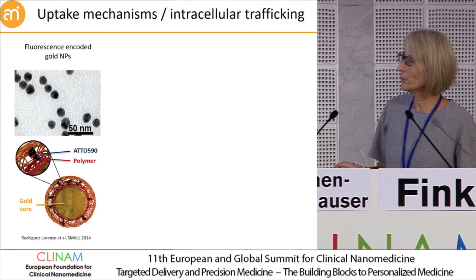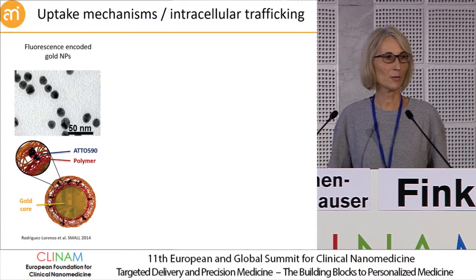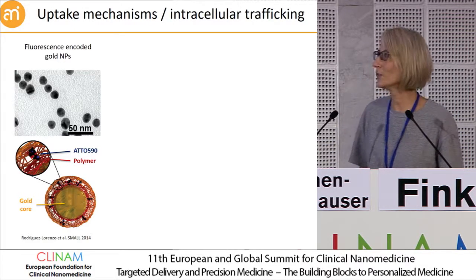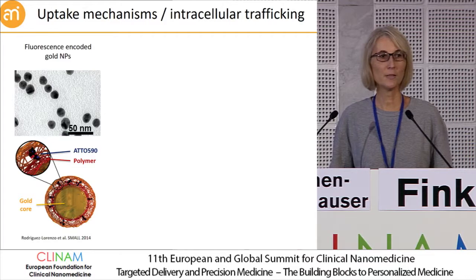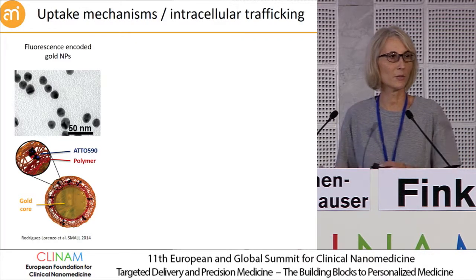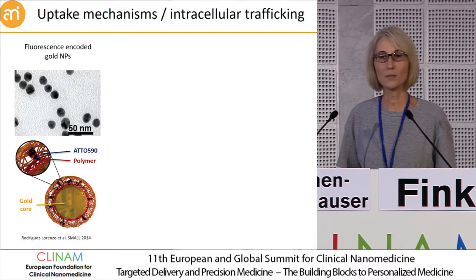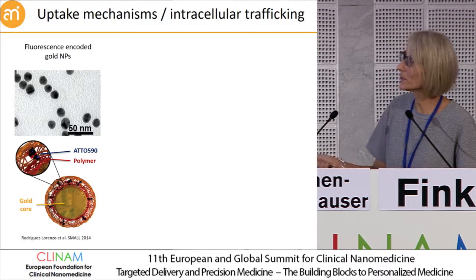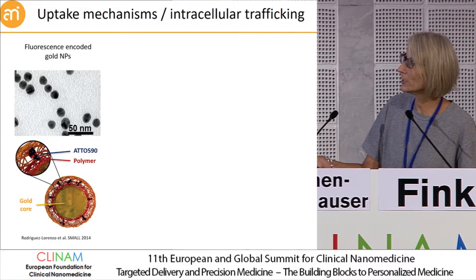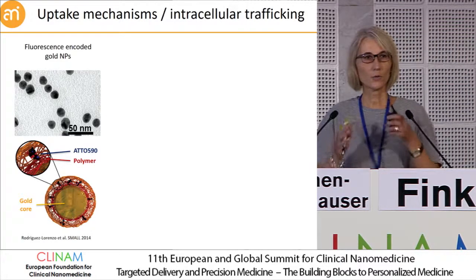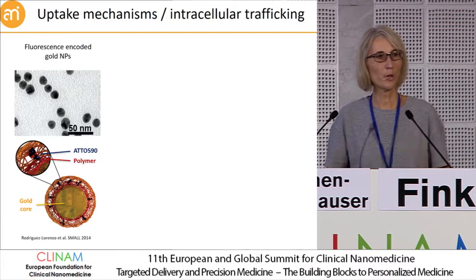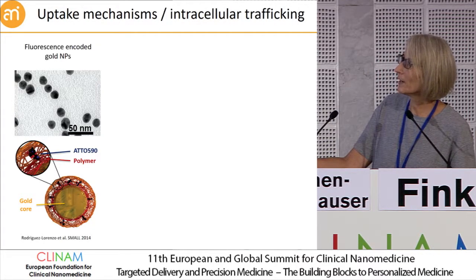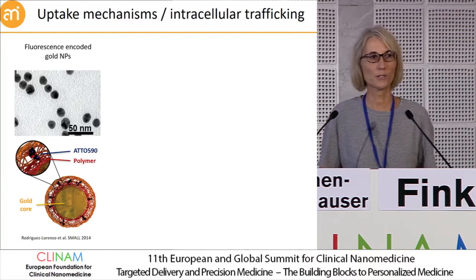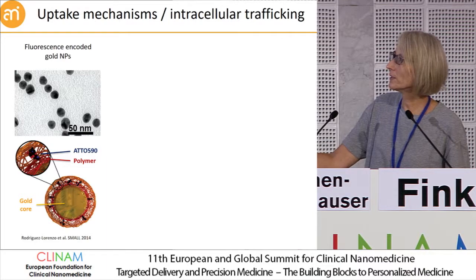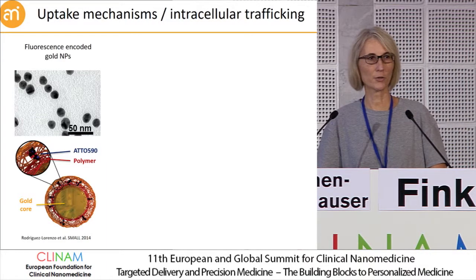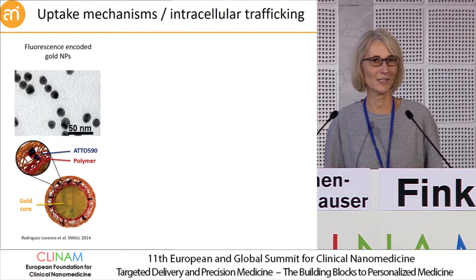So we have actually worked quite some years to produce these gold nanoparticles with a fluorophore on the surface, because gold is biocompatible, it is inert, it's not degraded, so it's quite nice also for animal studies to study the kinetics and the distribution in the organs. And so what we had to do is shield this ATTO fluorophore on the surface in a polymer, in 2 polymer layers, first to have a big enough distance from the gold core to avoid quenching, but also to avoid that the dye directly interacts with the cell surface,